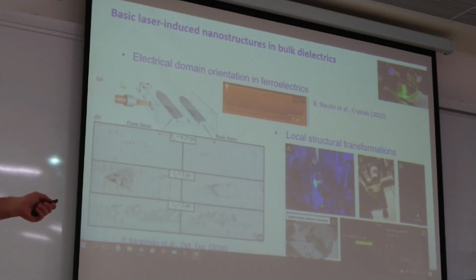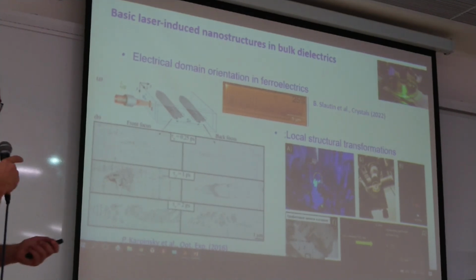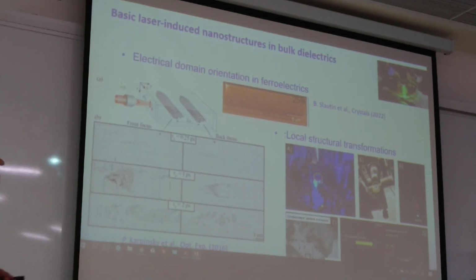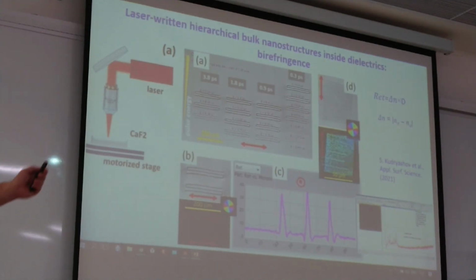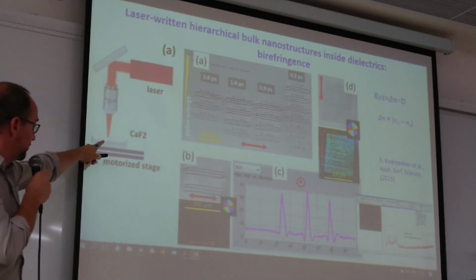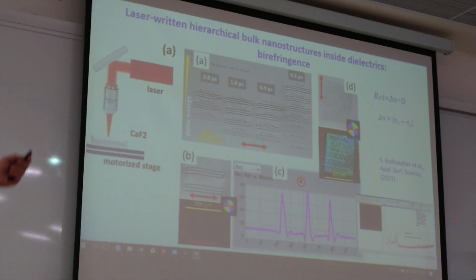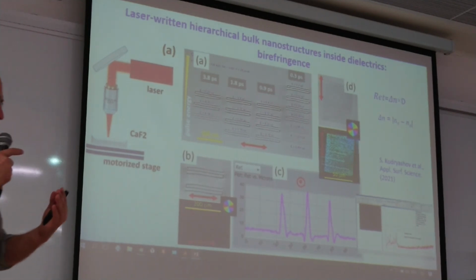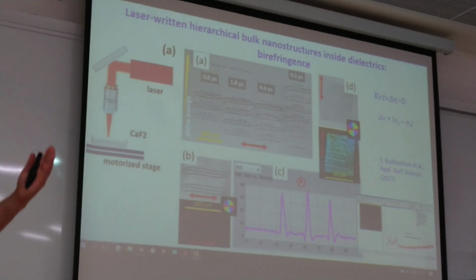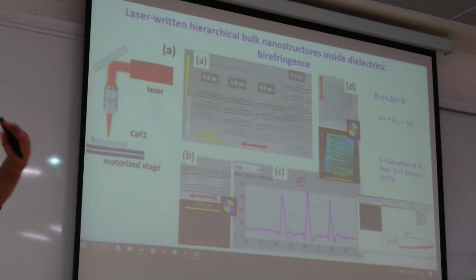And we have studied this closely. Oh, I probably can skip. This technology can be used also for electrical domain engineering in ferroelectrics, for example, to increase second harmonic generation. In our work, we studied the same structure, so the laser writes microbits of birefringent gratings in calcium fluoride. Calcium fluoride is a material making Frenkel pairs of fluorine vacancies and interstitials. So we use this to produce nanostructures.